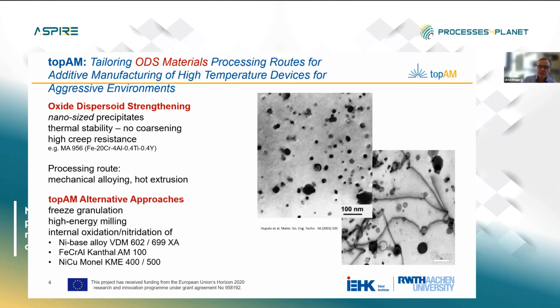We are developing alternative approaches for additive manufacturing, and I will introduce this later on. These are freeze granulation, high energy milling, and internal oxidation and nitridation. We are aiming at three different alloys: typical nickel-based superalloys, alloy 602 and 699, an iron-chromium-aluminum high temperature alloy, that is Kanthal AM 100, and for somewhat lower temperatures, alloy 400, a Monel type alloy, which was shown in a preliminary study to have very excellent resistance to metal dusting.